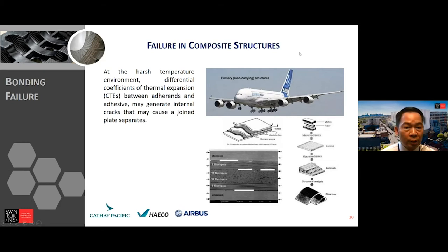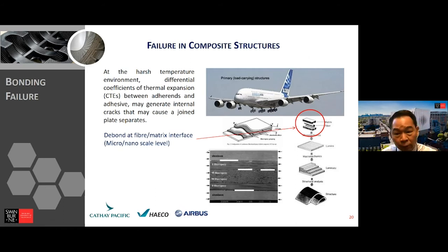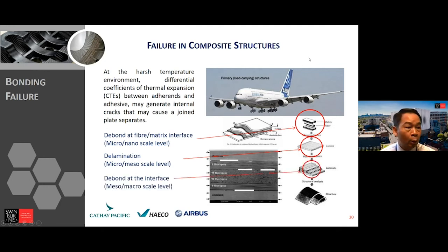So actually it's separated into three different levels. The first one is the fiber level, that is the bonding mechanism between the fiber and matrix. The second one is the composite ply level, that is delamination inside the composite. This one, if there's damage, is still acceptable at the early stage, because it depends on how serious the damage is. But the worst case is this one, debond.